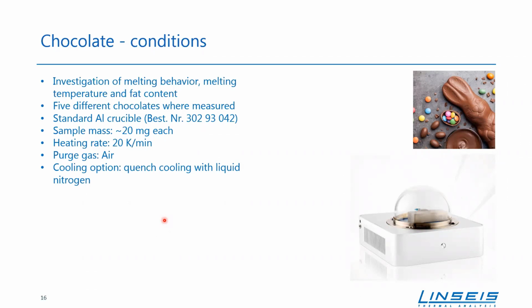Here, 5 different chocolate samples. We were interested in the melting behavior, the temperature, and of course the fat content. Also here we've used a ChipDSC 10 in combination with a quench cooler and liquid nitrogen in our standard crucible. In this case, we can use a higher heating rate of 20 Kelvin per minute because the peaks were broader. And we've measured here under air.